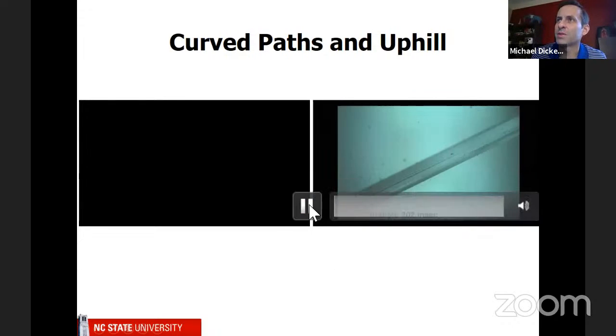So this has to be taken with a high-speed camera to see this. So you'll see this is a hill. And if you look carefully, it's actually pulling the film off of the surface. So let me play that one more time, because this was actually a really important experiment for us. If you watch, is it gonna work? There it goes. If you watch it, the leading edge of that droplet is sort of pulling that film off the surface.